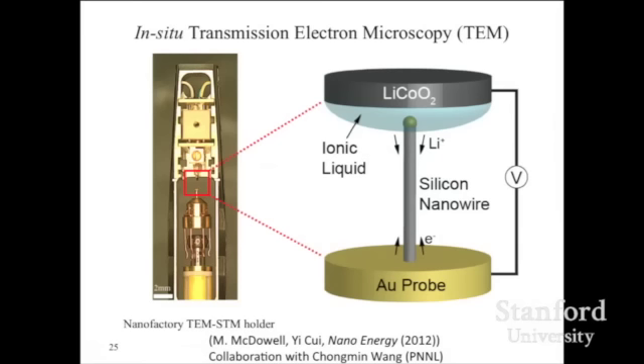You have some really nice in situ TEM videos of your batteries charging and discharging. I'm just wondering how you deal with beam-induced damage in those experiments. When we set up that in situ TEM, we intentionally avoid electron beam heating onto the organic electrolyte. You see right here, the reason we use this geometry is we insert the wires into the liquid, and the electron beam only looks at this. It doesn't damage this. If you look at the organic electrolyte, bad things happen very fast. But with that said, we still are careful, even though this is inorganic material. If you look at this at high energy, focused beam, you still induce certain changes. We can only take precautions, try to spread the beam so as not to introduce much damage. That's the only thing I can say.